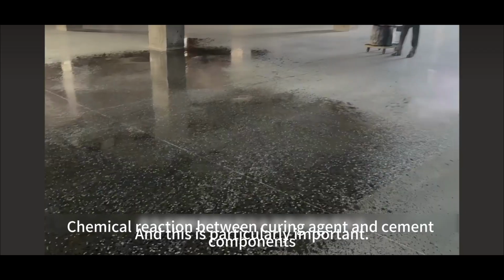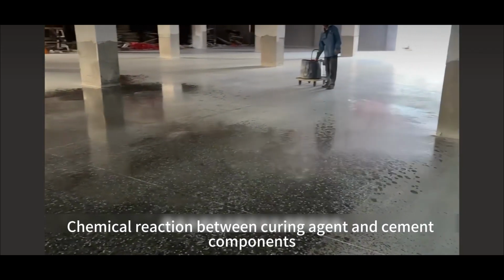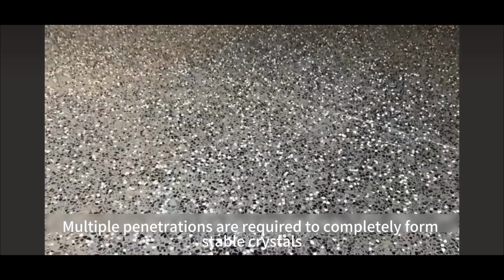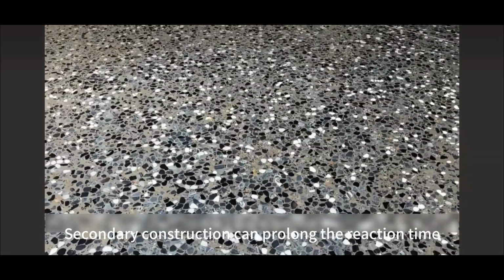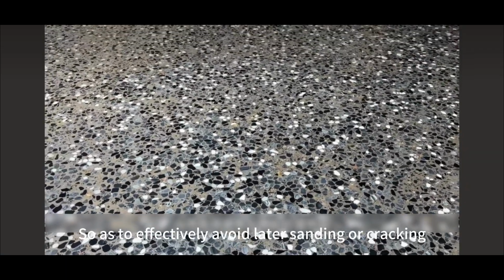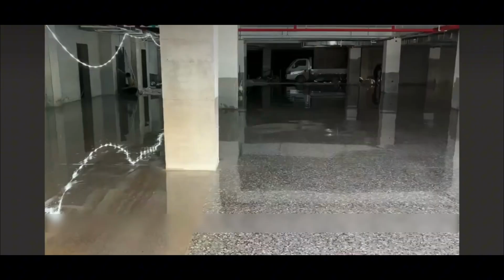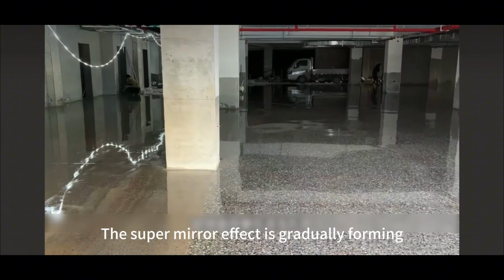And this is particularly important. The chemical reaction between curing agent and cement components requires multiple penetrations to completely form stable crystals. Secondary construction can prolong the reaction time, so as to effectively avoid later sanding or cracking. The super mirror effect is gradually forming.